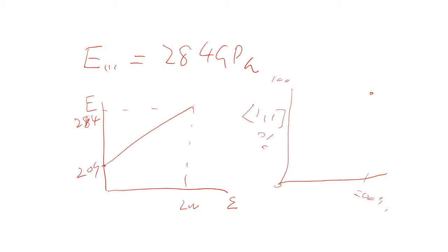And then at 0 strain, we're at some 111 that's close to 0. It's not exactly 0, because in a perfectly random texture, you still will have some 111, right? Okay. So the amount of 111 increases linearly with strain, and so the modulus also increases linearly, according to the approximations that I set forth in the problem.